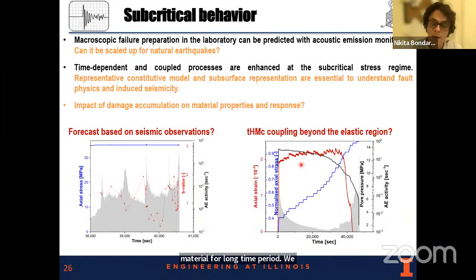We also collected acoustic emission data to try to find parameters which could help us understand this nucleation process. As a highlight, in the final stage the state of stress is not changing, but the acoustic emission activity, the microcracking activity, clearly shows spikes, and the relative distribution of energy of these events is changing.